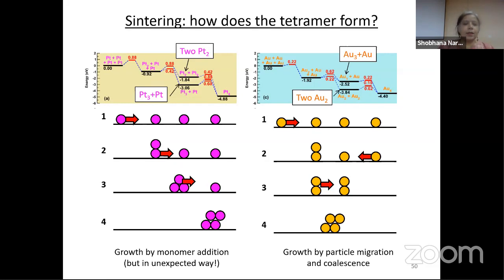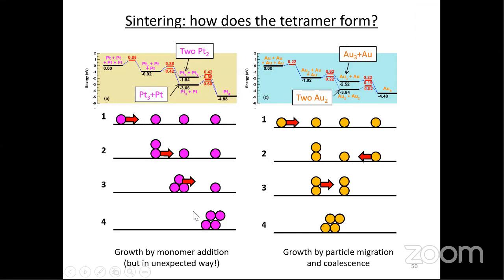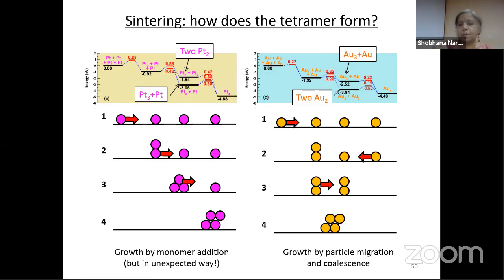And then you find, okay, so you look at it step by step. So let me do here a comparison of platinum and gold. And you see that here for platinum, the cluster is growing by one atom being added at a time. So it is a monomer addition process, but it is in a very unexpected way. Usually you expect that when you have monomer addition, it is the single atoms that diffuse and join up with the larger cluster. That is what happened in the video I showed you right at the beginning. But here it is happening by the opposite process. It is the larger clusters that are diffusing and joining the single atoms to form larger clusters.